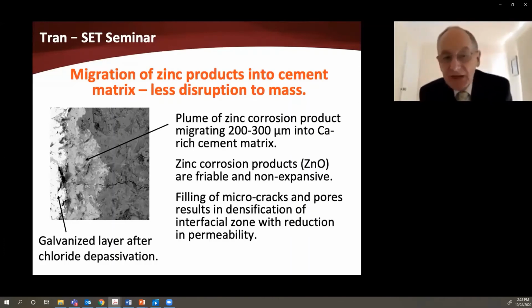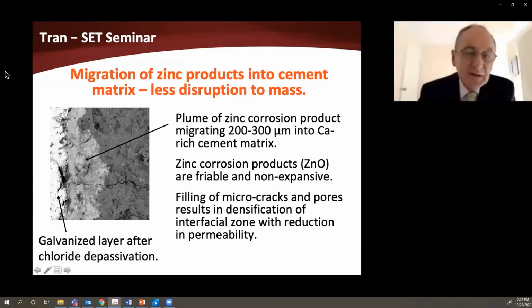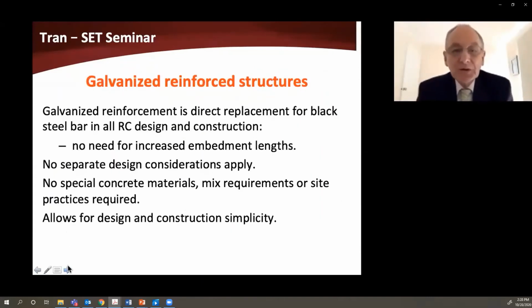So even though the zinc is starting to corrode because it's been depassivated, there's good evidence to suggest that there is still good long-term protection for two primary reasons. Firstly, you've got a lot of zinc that remains on the surface, and that needs to be removed before you get to the steel underneath. So there's a delay in the corrosion of the iron because of the zinc layer. And also the densification, the reduction in the permeability of the interfacial zone, does help to prevent further diffusion of chlorides and the like to the surface. So let's talk a little bit about the design side and fabrication.